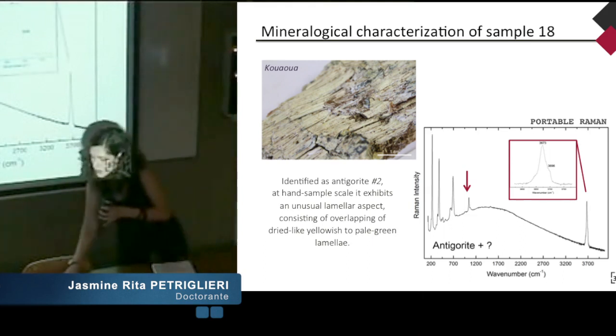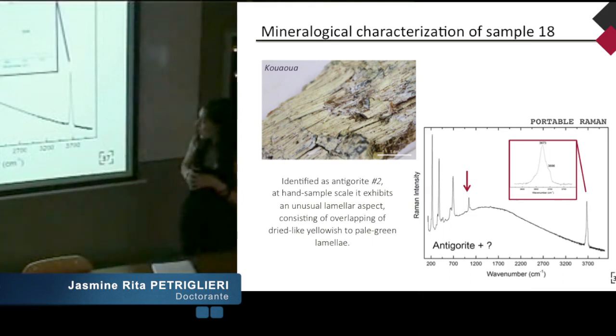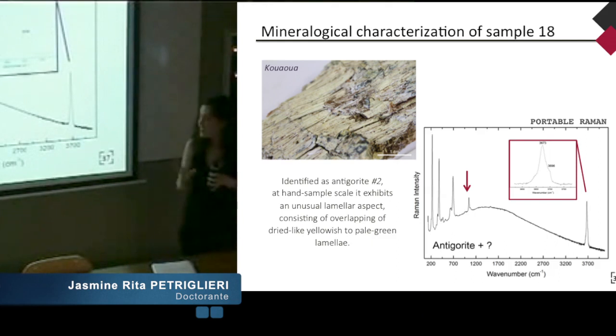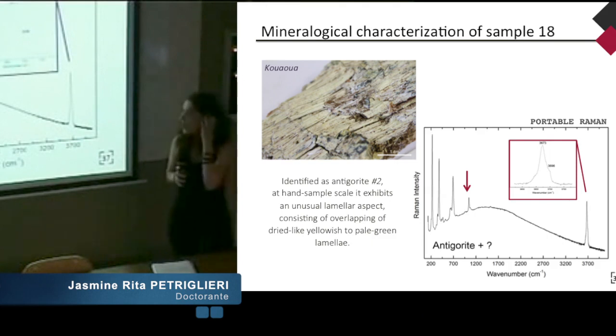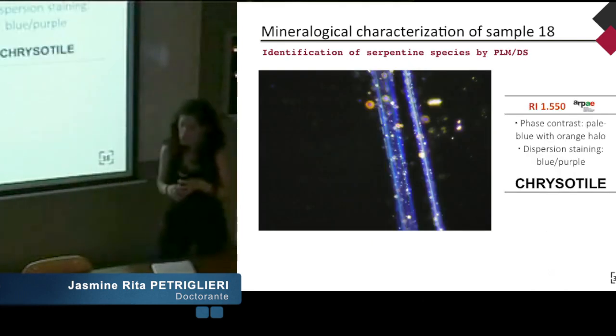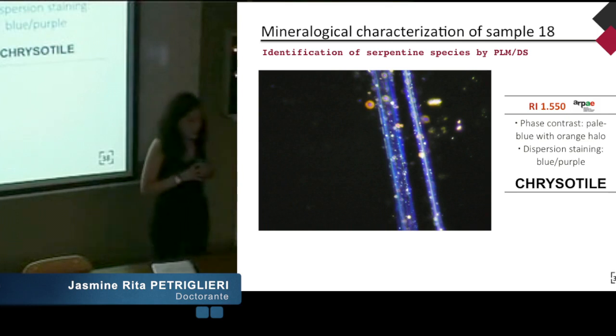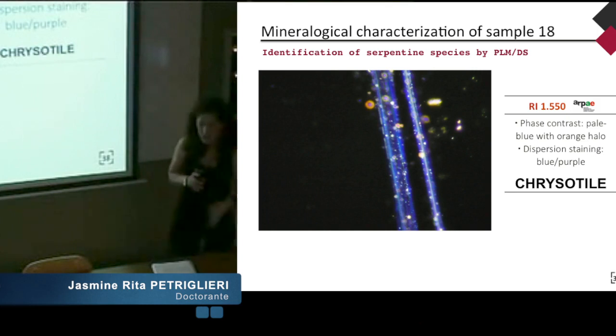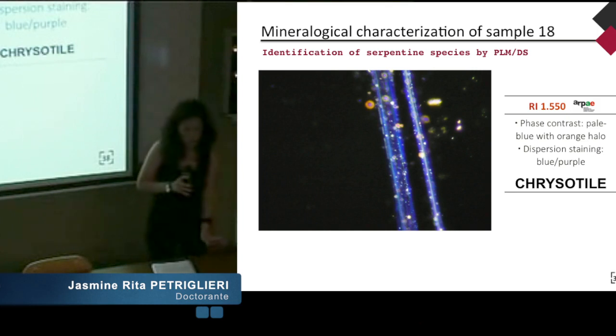Preliminary results obtained with portable Raman demonstrate that at the lower wavenumber region we observe the typical Raman peaks spectra of antigorite. Conversely, observing the OH stretching vibration, the doublet of antigorite is shifted to different wavenumbers, which suggests the presence of secondary serpentine minerals. To study this sample by optical microscopy associated with dispersion staining, we need two minimum refractive index liquids: one for chrysotile and one for the other variety of serpentine.